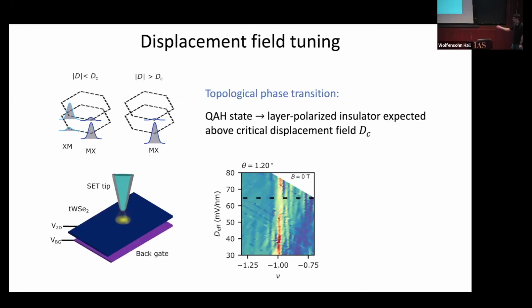We are limited here. With the tip, we can apply a potential difference between tip and sample, and this indeed gives us some tunability of the displacement field, but our tip is narrow. And so what that means, you can sort of see it in this stylized image, is that the effective gating from the tip is different depending on where you are in the sample. Right under the tip, that's where your displacement field is strongest. As you move away, the effective displacement field gets weaker and weaker. You get less doping from the tip. And so actually, there's some inhomogeneity to the doping profile. That's why you see all these extra wiggles starting to appear as you go higher and higher in displacement field.